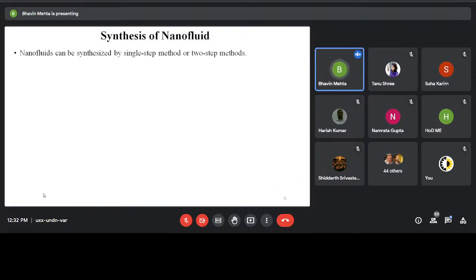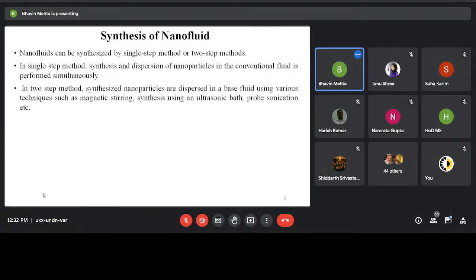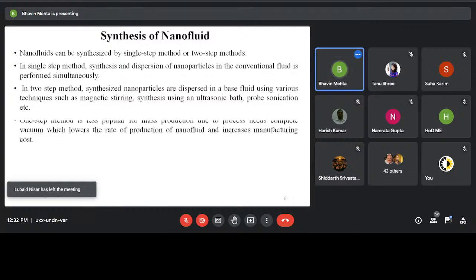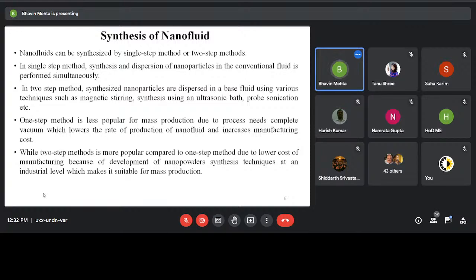Nanofluids could be synthesized by a single step method or a two step method. In a single step method, the synthesis and dispersion of nanoparticles in the conventional fluid is performed simultaneously. While in two-step methods, the nanoparticles are first synthesized and then dispersed in the base fluid with the help of mechanical stability techniques like magnetic stirring, an ultrasonic bath, probe sonication, and combinations of them. The one-step method is less popular for mass production due to the infrastructure required, which causes higher manufacturing cost, while two-step methods are more popular for the development of nanofluids.